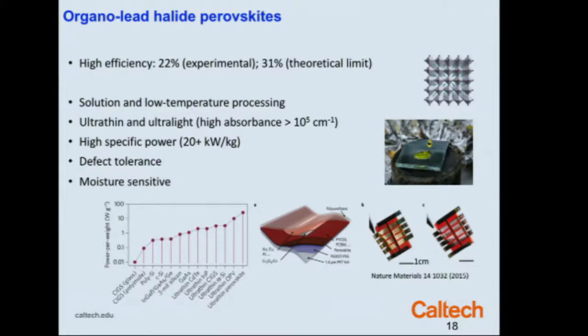So one of the materials that has been leading the worldwide research community on an incredibly energetic development cycle over the last 5 years are the so-called organo-lead halide perovskites. This is not an oxide perovskite that is familiar to many of you. It is a perovskite crystal structure, but one which has halogens like iodine rather than oxygen on the perovskite octahedral, and it has typically organic cations, and then uses something like lead as the center B atom in the ABX3 crystal structure. These materials are remarkable photovoltaic materials.